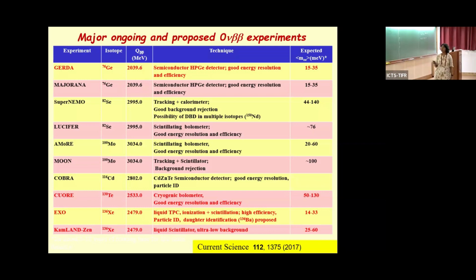And then people jumped to germanium, because you can make a very high resolution detector. In the meantime, EXO and more so KamLAND had set up a detector for a reactor neutrino experiment. When that was over, they just made a xenon-loaded liquid scintillator and improved the background. So what finally goes into the T sensitivity is B delta E, right? Background and the resolution. So they achieved a much better background. Today the best limit is actually from KamLAND. As you see, these all have reasonably high Q values.